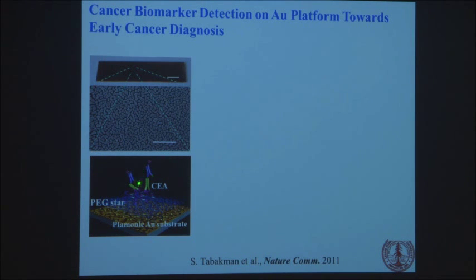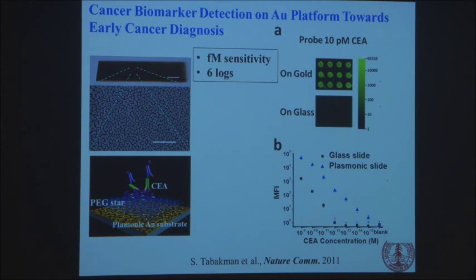In this case, we're capturing a cancer biomarker, CEA, and we want to see what concentrations of CEA we can detect on the gold, because we can enhance the fluorescence. It turns out we can get down to femtomolar sensitivity. This is a concentration range from nanomolar to femtomolar, and you can see we get a linear detection all the way to femtomolar. On glass, the signal is much weaker. This is log scale, so a much weaker signal, and you lose sensitivity below about 1 picomolar. This is very, very reproducible. And if you look at the images, you can tell right away it is much brighter on gold than on glass, so you have a very high enhancement of the signal.